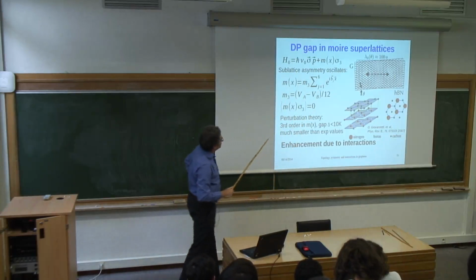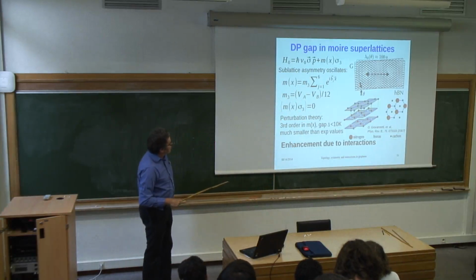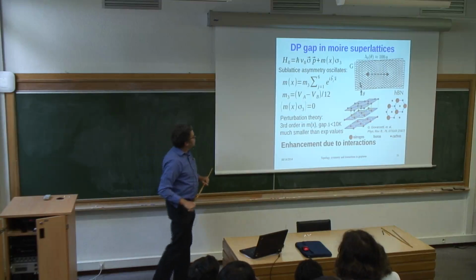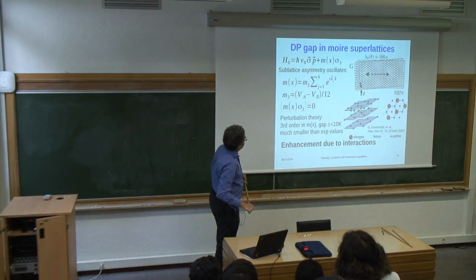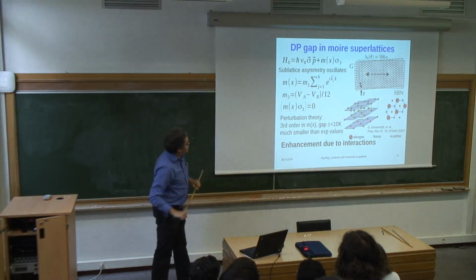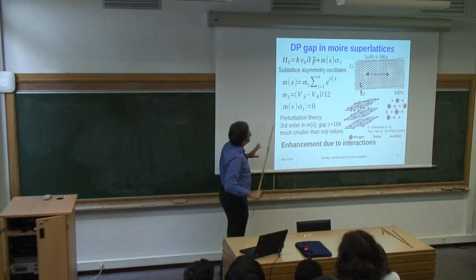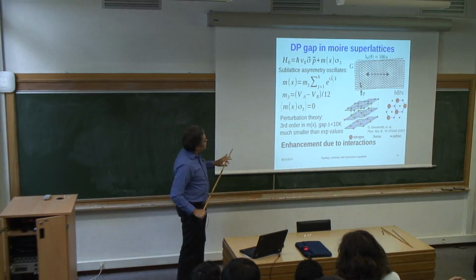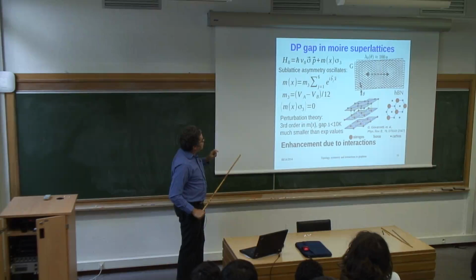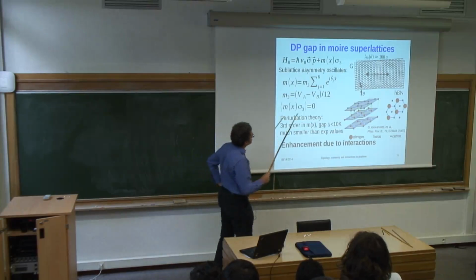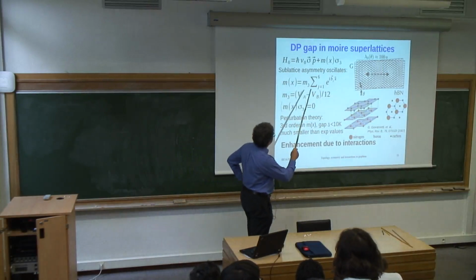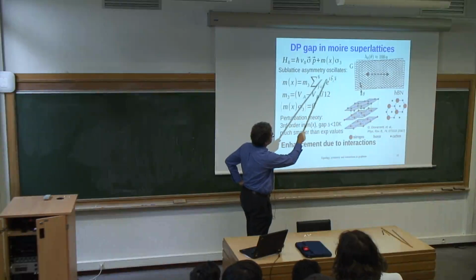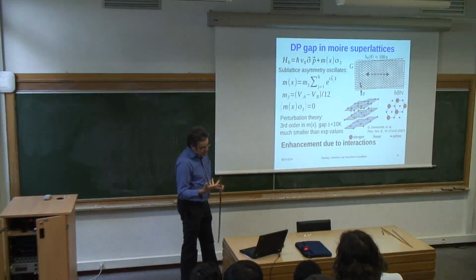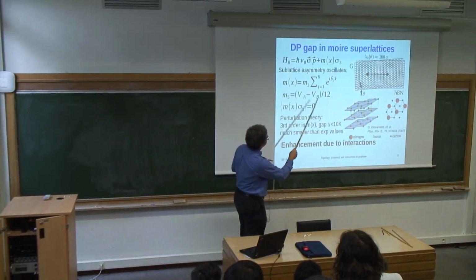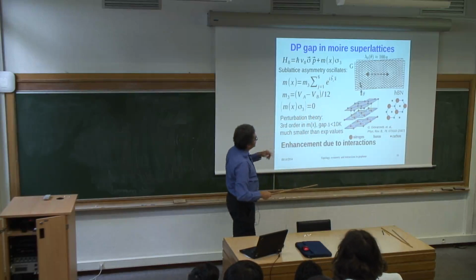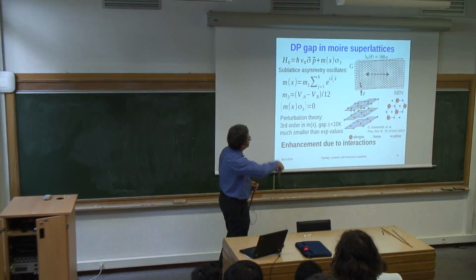adding a spatially modulated mass term to the Dirac equation, and then before you turn on interactions, you can ask what this term does on a single particle level, and it will open a gap at the Dirac point, but only at third order perturbation theory, because you need to get a contribution in which the modulation vectors add up so that you get a zero net vector. Each of these produces Bragg scattering with the superlattice vector B, and you need to scatter 3 times in 3 different directions to get back to where you started.